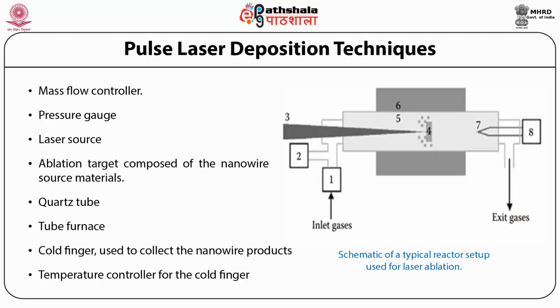The laser, when it hits the target, generates a plume containing vapor fragments of the target. The target is made by pressing the source materials and the catalyst metal together into a solid cylindrical pellet. The chamber temperature is maintained using the tube furnace at a level needed to sustain the catalyst molten alloy for nanowire growth, typically between 800 degrees Celsius to 1200 degrees Celsius. The variables in this method include laser power, target composition, gas phase composition, temperature, pressure, residence time of vapor phase species, and cold finger conditions.